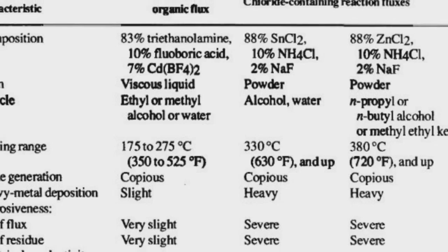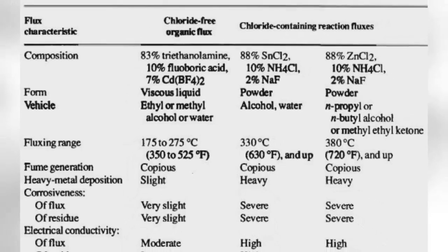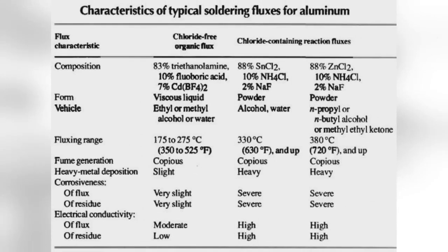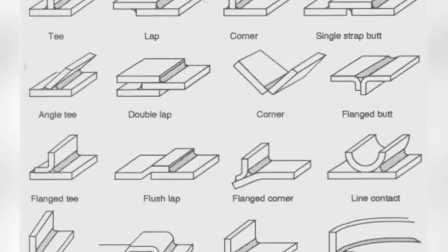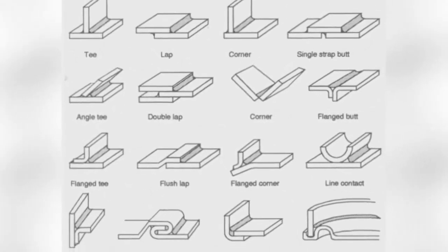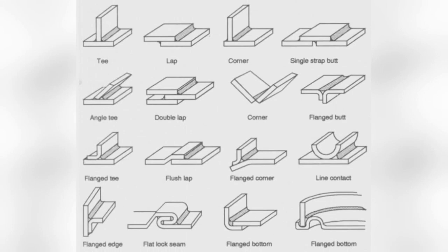Fluxes for soldering aluminium are of two types: organic fluxes and chloride-containing, inorganic salt, reaction fluxes. When heated, organic fluxes react with the oxide film and remove it from the aluminium. Reaction fluxes penetrate the oxide film and contact the underlying aluminium. Joints to be soldered with flux must be designed to permit application of the flux. Provision must be made for the flux to be displaced by the filler metal, because entrapped flux is a potential source of corrosion. Joint design must also allow the escape of gas and subsequent penetration by filler metal to ensure the complete distribution of filler metal in the joint.